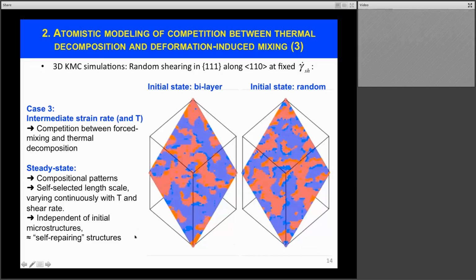There's another point that's interesting already to notice, which is that in some way these structures are self-repairing, because if we were to change temporarily the temperature or the strain rate, you'd see that the system might evolve dynamically, and then as you would return to a lower temperature or the initial temperature, the structure would readjust to the original operating conditions.